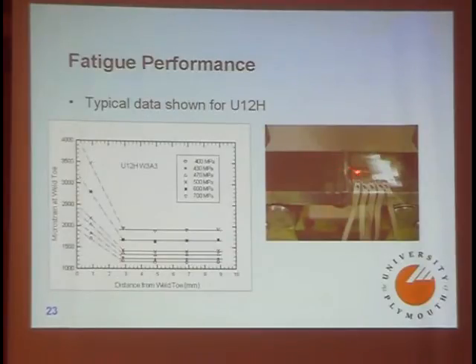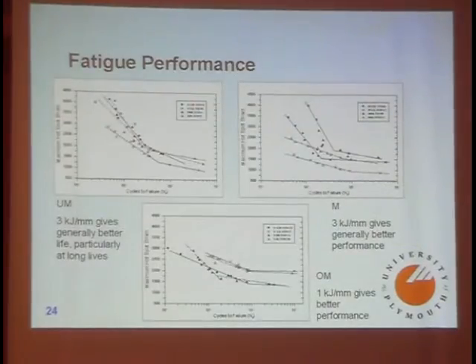So this is how we've done the hotspot strain measurements. There's the strain gauge, there's the weld. This is the sort of data you can get. Again, we don't have enough points close to the weld to really extrapolate this terribly well, but we have done a little bit of FE work that indicates that it's at least reasonable. And you can then get out the hotspot strain fatigue performance. These things get rather busy, so I split them out into undermatched, matched, and overmatched. But you can see there are a variety of different slopes here. So the data is quite scattered.